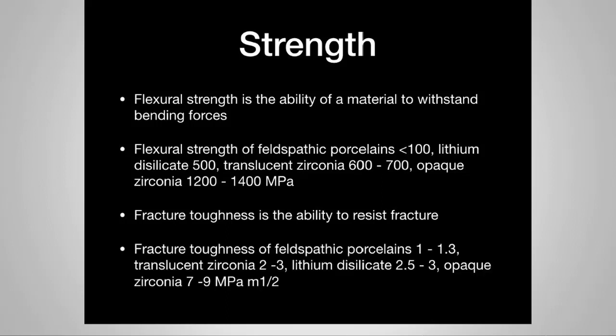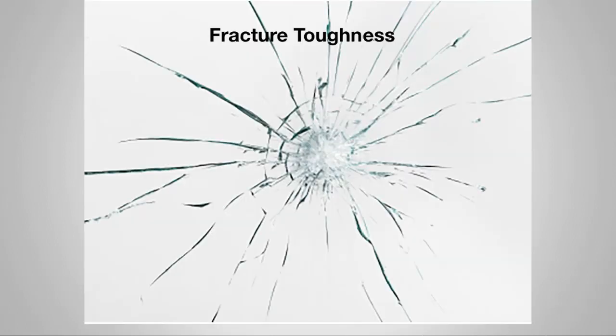So feldspathics, once again, weaker of the ceramics, you're going to have 1 to 1.3. And then translucent zirconias, remember that's the 5 molar, you're going to get between 2 and 3. Lithium disilicate, which is that material that we've all used and love, is 2.5 to 3. So you see quite a bit of overlap there. And then the opaque zirconia is going to be 7 to 9, quite a big jump from 3 to 7. So fracture toughness is something that is a really nice way to think about strength for zirconia.